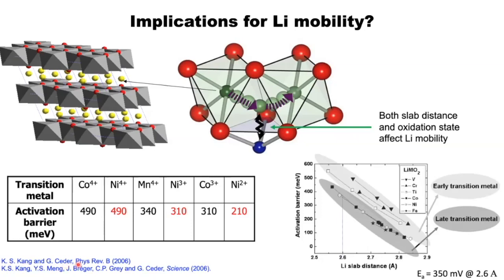What Gerd's group did by DFT was to determine the activation barriers as a function of the slab layer. Lithium mobility in the lithium layer involves a hop from an octahedral site through a tetrahedral site to another octahedral site. The tetrahedral site acts as the transition state or the intermediate in the hop from octahedral site to octahedral site. And the distance between the tetrahedral site and the metal in the layer below is a direct control of the activation barrier for that hopping process.